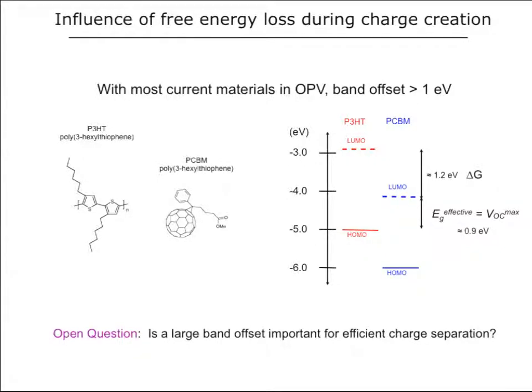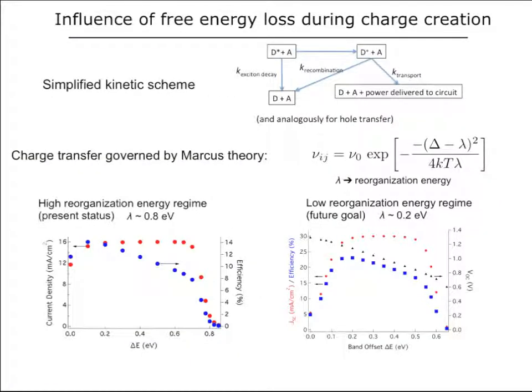So the question is, how much energy do we need to lose to drive the reaction? One can expect that we need some driving force to drive the reaction. But if it's too small, then we don't induce this event. So that's really an open question in the field, is how large can that, or rather how small can the delta G be, and therefore how large can the voltage be? So there's a number of different groups looking at this through synthetic chemistry to change the band offsets. And let me just offer one perspective on this problem.